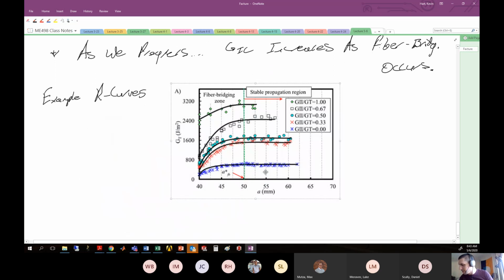All right, so this is sort of real life data. And what's happening here is that initially when the test starts, so let's take a look at this line, for instance. Initially when the test starts, we're here, and no fiber bridging has occurred. So my value of the critical strain energy release rate is relatively small. So this must have been the initial crack length. Then as the crack propagates, more and more fiber bridging occurs, and it becomes harder and harder to open it because there's more and more of this bridging effect. And so what you see is this slow rise in the R curve until you get to some plateau,